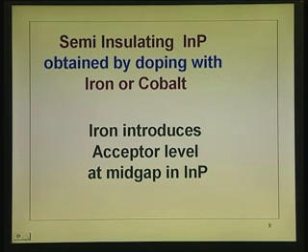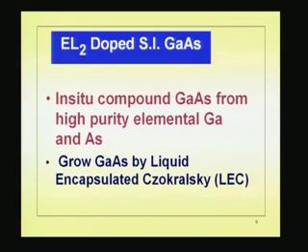You can rest assured that if you do not take care with the usual crucibles which you use, if you use a silica crucible, that will be silicon, that will get doped from that. So, that is why they comfortably use compensation like that.